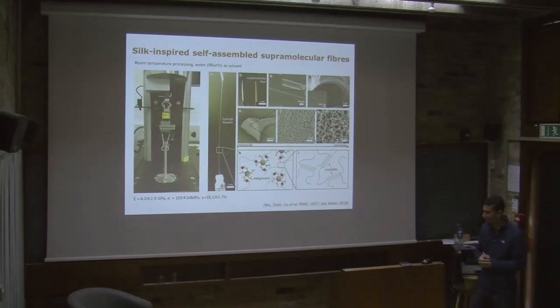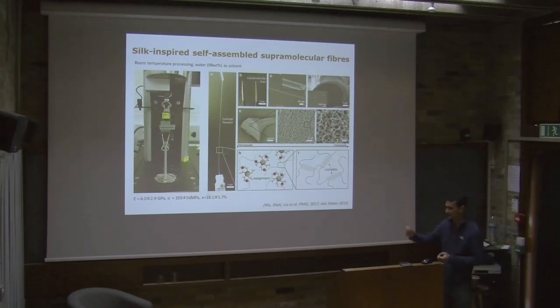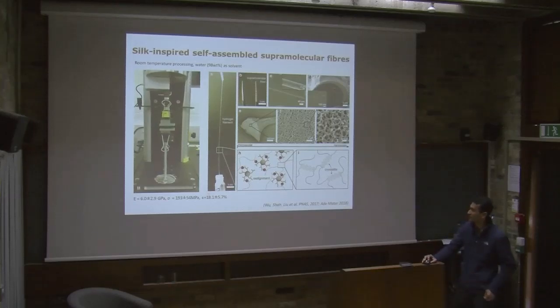And then more recently, we've been trying to recreate synthetic silk, and we've done that in collaboration with the chemistry department, taking two fundamental materials. We took silica, which is basically sand, and modified it with some polymers, and used hydroxyethyl cellulose, which is again a cellulose derivative, a sugar derivative, and we mixed them together using a very special molecule called cucurbituril, which is donut shaped. What this molecule does is it makes the first two polymers or molecules hold hands, so it handcuffs them together, and it has to be in that fashion. It makes it self-assembling, so that it's only these two that are handcuffing together and not one cellulose molecule with another cellulose molecule. And when you mix them, you can form these highly elastic hydrogels and fibrous materials.